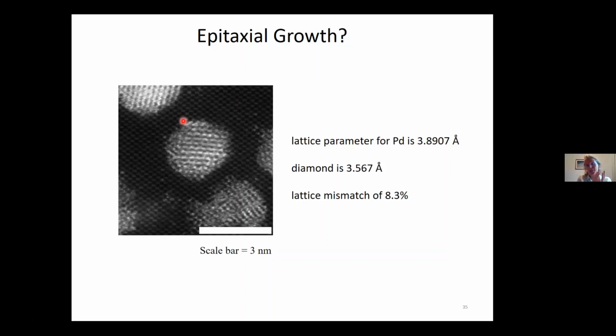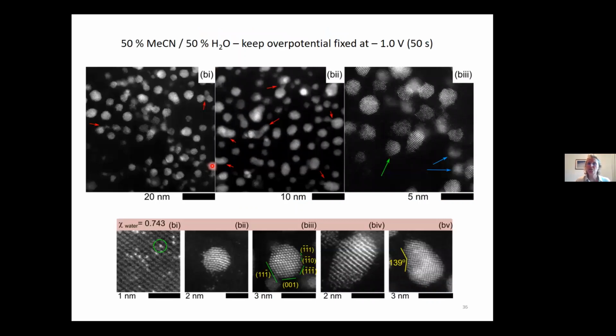It's like we're doing single crystal electrochemistry or kind of electrochemical microscopy. When we looked with the microscopist at these images, they said it almost looked that there was starting to be evidence of epitaxial growth, that the underlying crystal structure of the BDD was actually influencing the formation of the alignment of the nanoparticle.